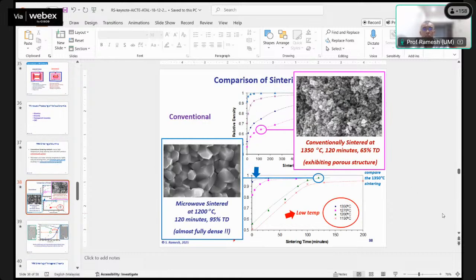This is typical, showing the structure of conventionally sintered alumina, where it is not possible to get high density at a low temperature of 1350 degrees holding for 2 hours. For 1350 for 2 hours, the density is about 65% dense. And the structure is porous.